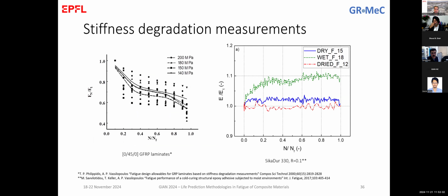I'm showing measurements, and in this case, I come back to the measurements that we have seen yesterday for the adhesive material. And there is exactly the effect of the conditioning of the material, or the conditions of the testing or of the operation of the structure. But in some cases, as we've seen also yesterday, we might have stiffness that is increasing instead of decreasing. And this can be due to the plasticization in this case, due to additional curing of the material with time, in other cases, due to the alignment of fibers in the system that we've seen for plus minus 45 degrees.